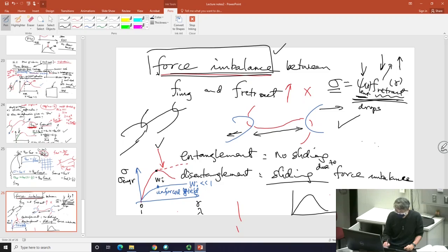Again, my favorite case, this limit, you can never lose them. They're just voluntarily, meaning when one disappears, next one comes back up, meaning they are in equilibrium. This is the weak flow limit. You never lose anything. There's no force imbalance to speak about. There's only the diffusion trying to compete with your imposed deformation.